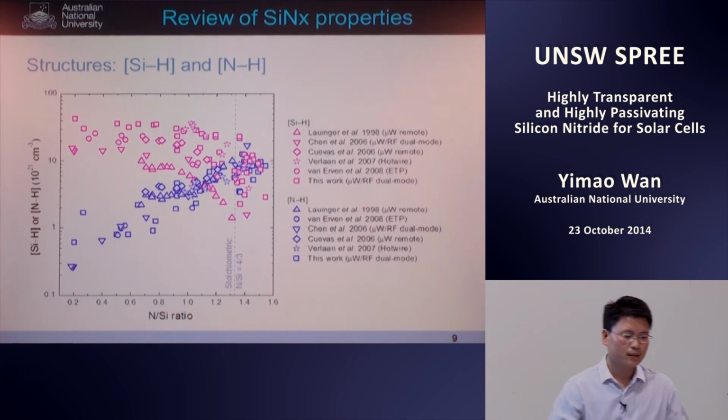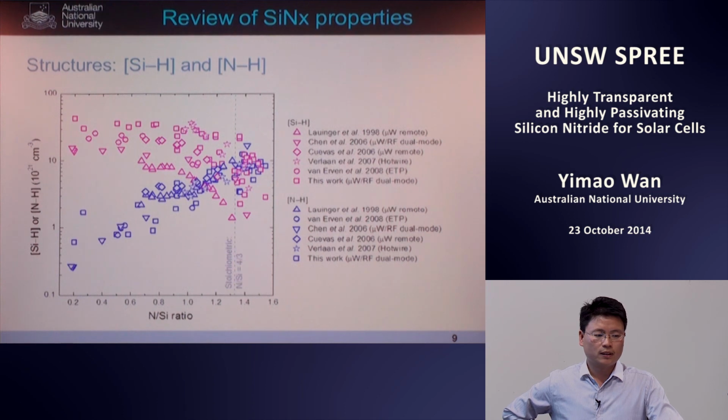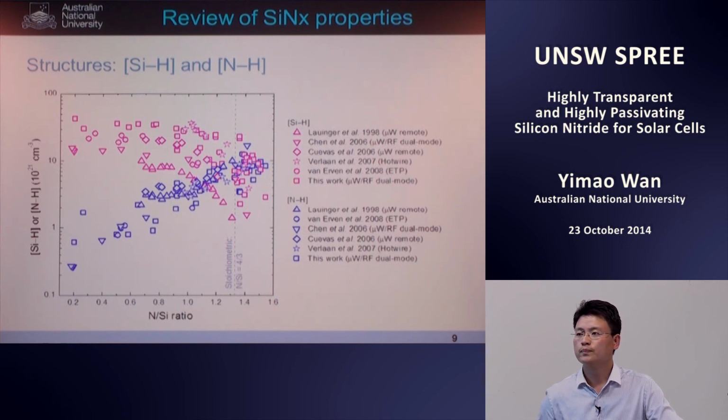Okay. Yeah, if you use the model proposed by Girisch in 1988, you can still add in the contribution of charge into the formula. I don't have the details of the spreadsheet here, but it is possible to incorporate charge into the model. The charge will impact the n_s and p_s, the concentration of the excess carriers near the surface, and this goes into the Shockley-Read-Hall equation. So that will help you calculate the concentration at the surface, which is different from the concentration in the bulk.